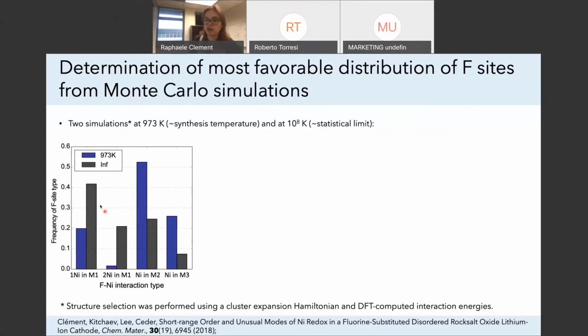So these ones have one nickel directly bonded to them. These ones have two nickel directly bonded to them. These ones have no nickel directly bonded to them, but nickel in the second coordination shell. And these ones have nickel in the third coordination shell only. And what we find is that in our material, we have clear short range order. And so fluorine here has very few nickel nearest neighbors directly bonded to it.